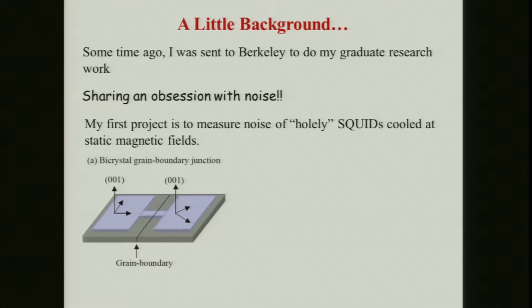At that time, at Clarke Group, we were working on the high temperature superconducting devices, and we used the bicrystals. So you take the substrate with a grain boundary in between, you deposit YBCO on top of it, and then you pattern them. Also at that time, John told me, Gene Dansko just did a thesis, and they talked to John Clem. Apparently, if you apply magnetic field to your films, there is some kind of relationship between the vortex flux pinned at your film and the film width.